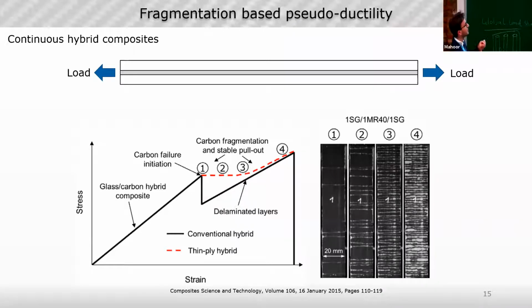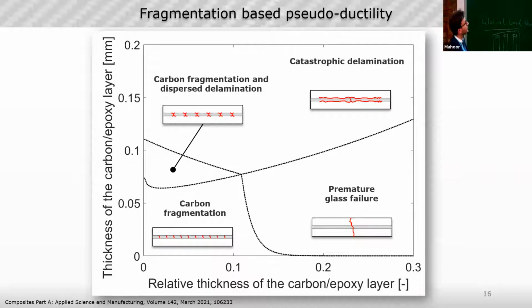But in this case, the fragmentation requires that the central layer, the low elongation material, which in this case is the carbon one, starts to fracture, and it forms multiple fractures with increasing load. Most of you most probably know this map, called the damage mode map, and it explains clearly that to achieve the fragmentation of the material, we need a strict rule about the design of the hybrid material. First of all, as you can see, in the vertical and horizontal axes, one of the common parameters is the thickness of the central layer. So the carbon layer must be really thin, or at least thin enough that as soon as it breaks, the energy released by the fracture is lower than the fracture toughness at the interface of the material.